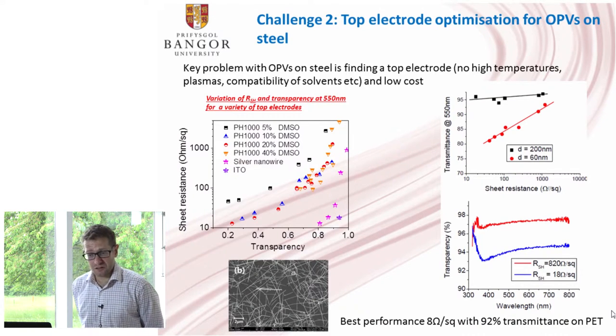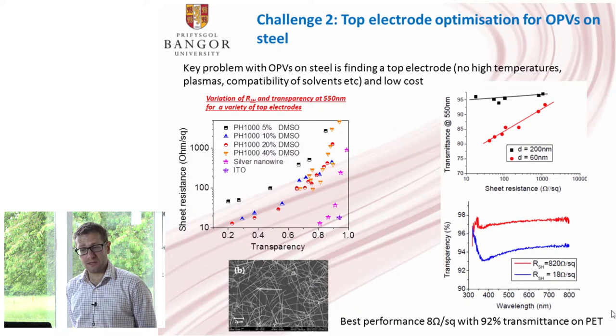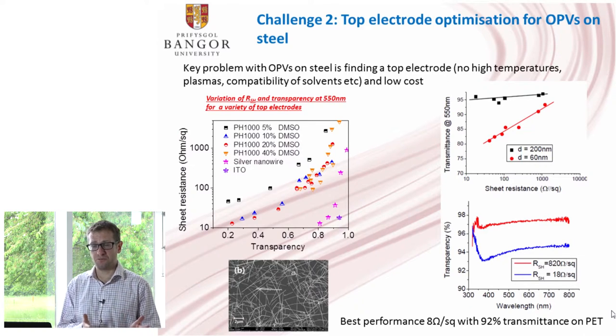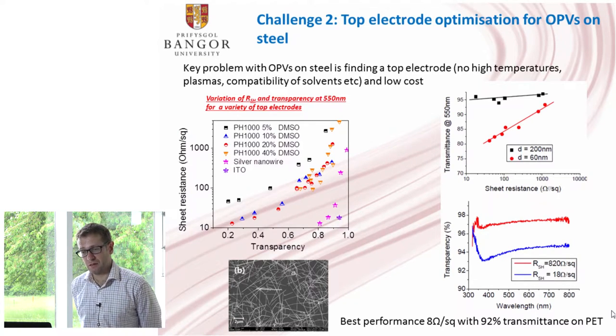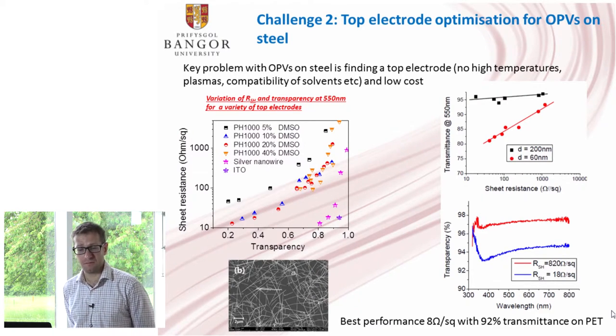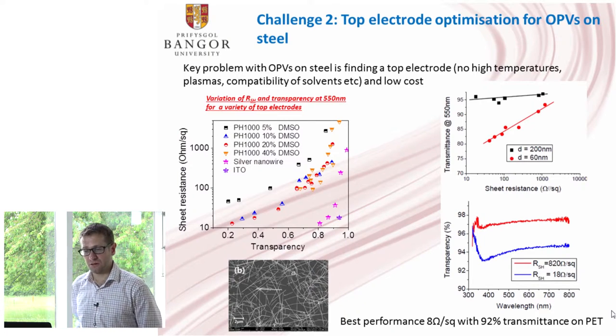There's a second major challenge in developing organic solar cells on steel substrates, and that's finding a good electrode. Typically we spray coat a composite electrode, which consists of PEDOT and silver nanowires. PEDOT on its own, we tend to mix with a high boiling point solvent, such as DMSO. Unfortunately, we can't get the sheet resistance of these layers down to an acceptable value whilst maintaining good transparency. So we spray coat on a silver nanowire layer as well, so it becomes a composite electrode.